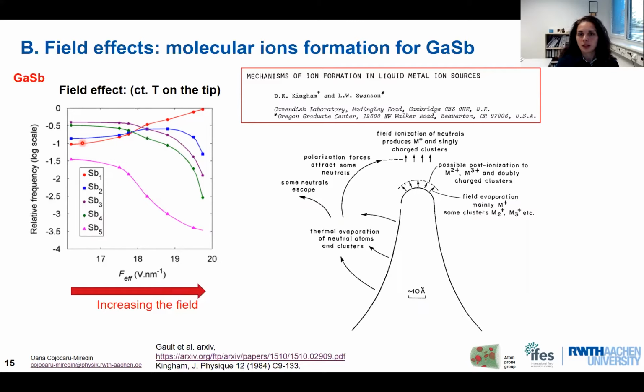And if we now use the same model and try to explain the formation of the cluster ions, this can give us, of course, some hints. So if we have here a Taylor cone or a tip-shaped specimen, and we place a very high electrical field on the apex of the tip, of course, we have possible post-ionization processes, and this we can see on the mass spectra, the presence of double charge or triple charge ions. But we have also the field evaporation of some clusters like M2+ and M3+.